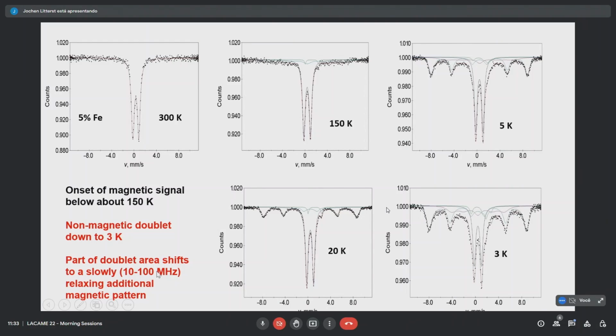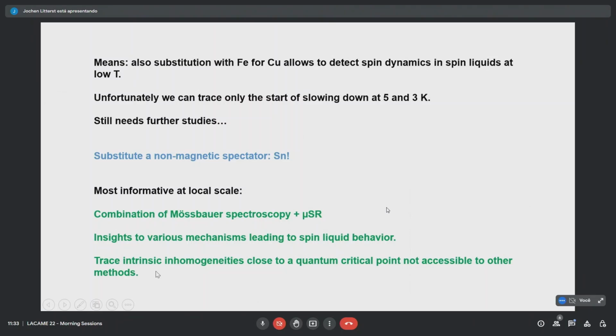So that gives us a possibility now also to look at such a quantum spin liquid by means of Mössbauer spectroscopy. Unfortunately, as I told you before, we can see only the start of this slowing down at 5 Kelvin and 3 Kelvin, but we cannot go lower. So what should go far lower? That means we need further studies.